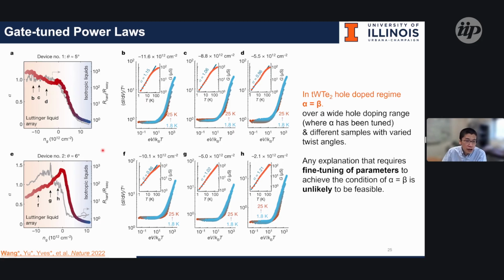We can reproduce this observation in two systems: one with a twist angle of 5 degrees, and another with a twist angle of 6 degrees. We can use this approach across many systems.